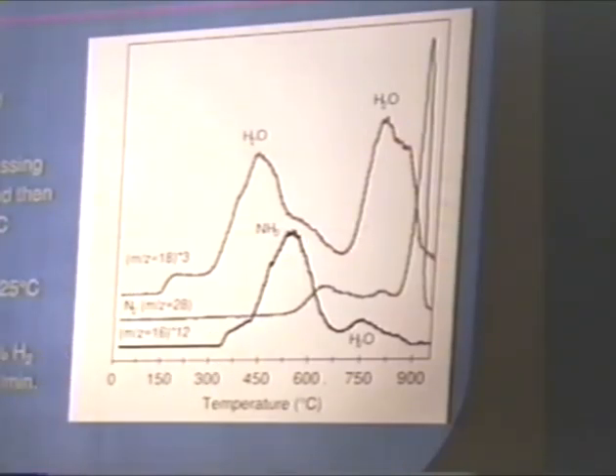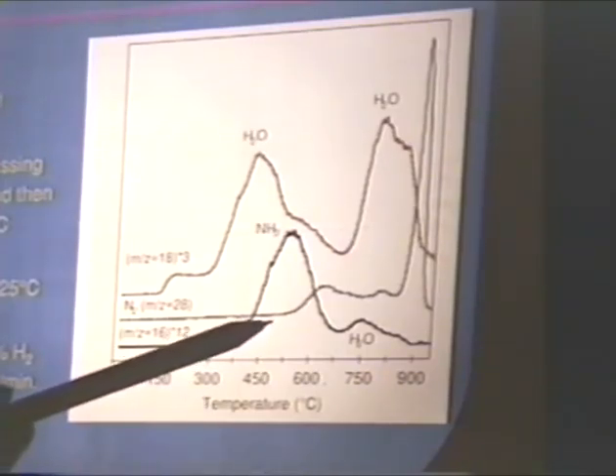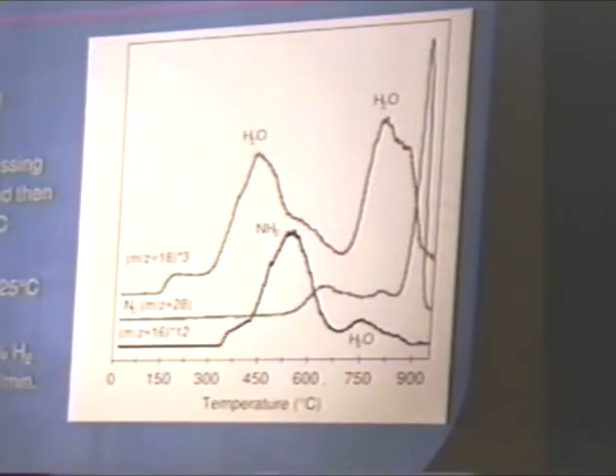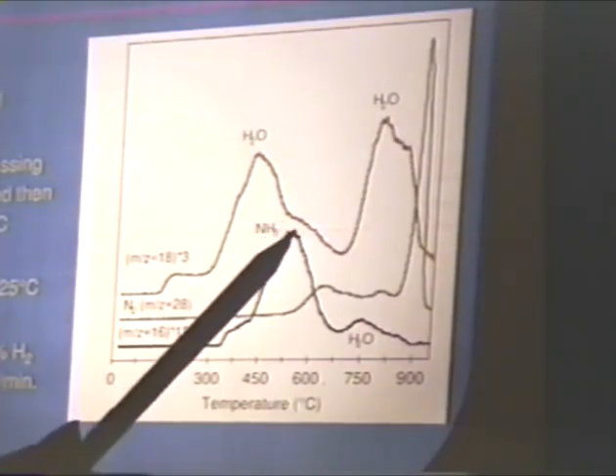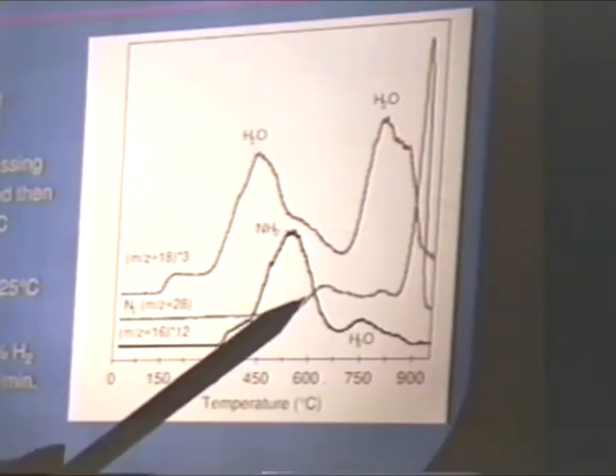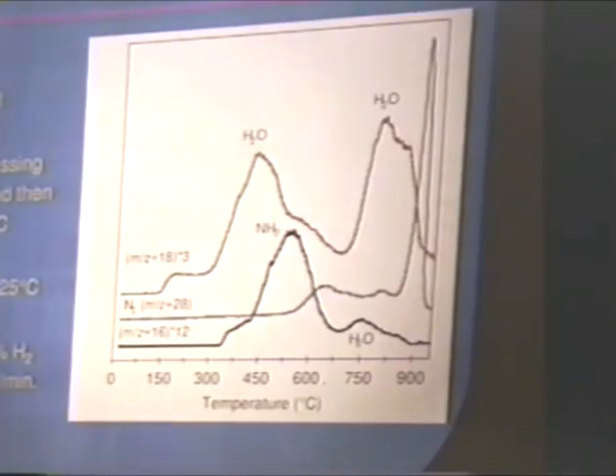Again, I'd like to point out that these are much weaker signals, especially ammonia. We start at a maximum around 450 or 500 degrees centigrade, but the maximum for ammonia coincides with the onset of the nitrogen signal here. We suspect that the early nitrogen evolution that we see from the surface may be due to decomposition of ammonia, which in independent experiments we have shown can decompose at these temperatures over some of these similar catalytic materials.